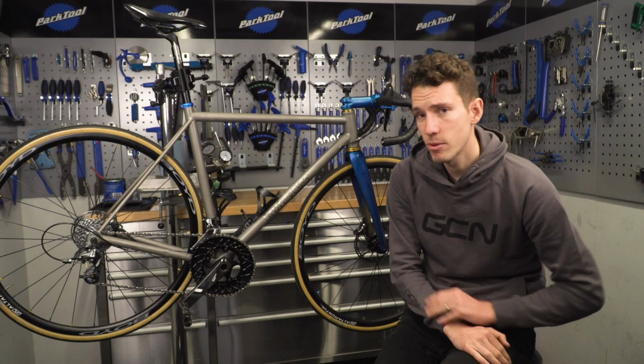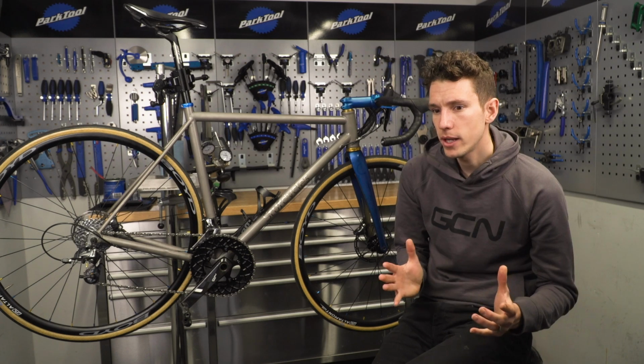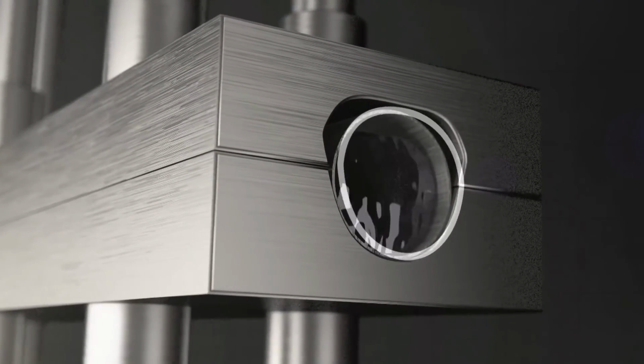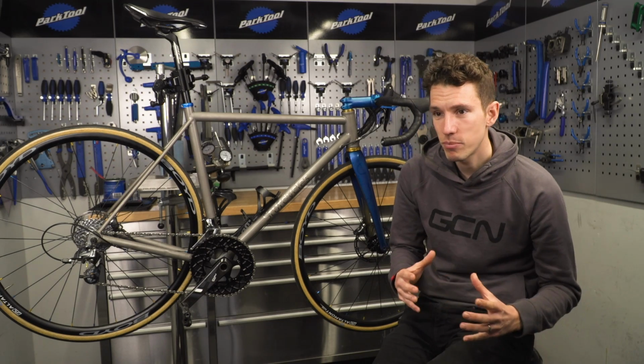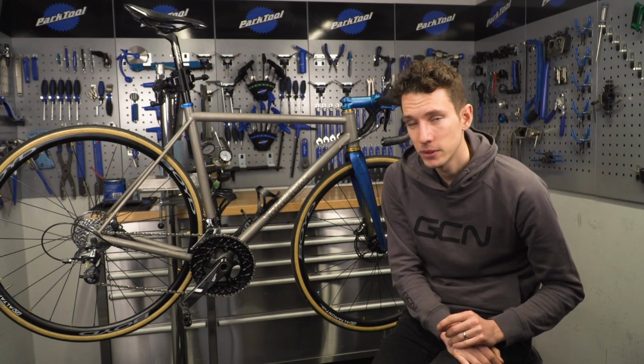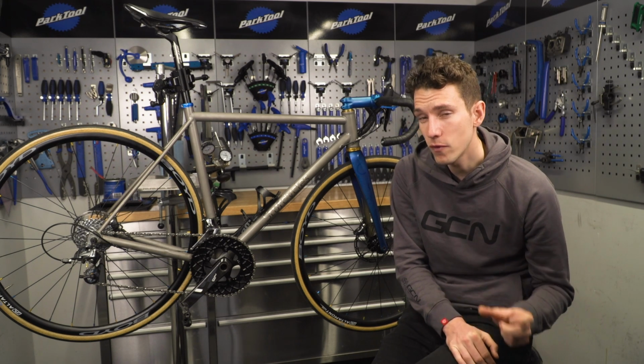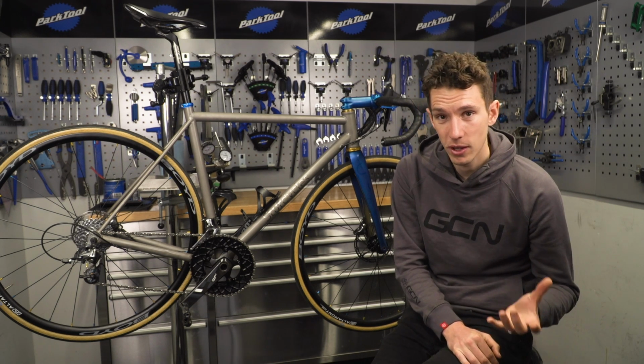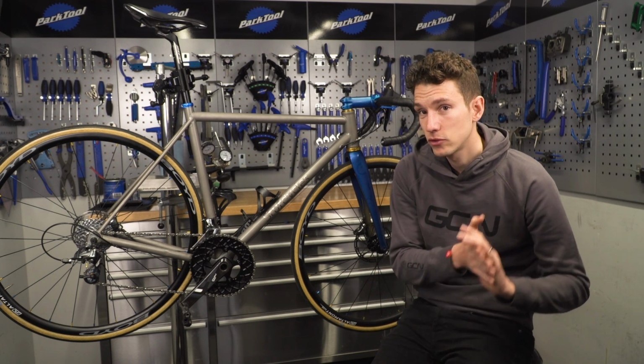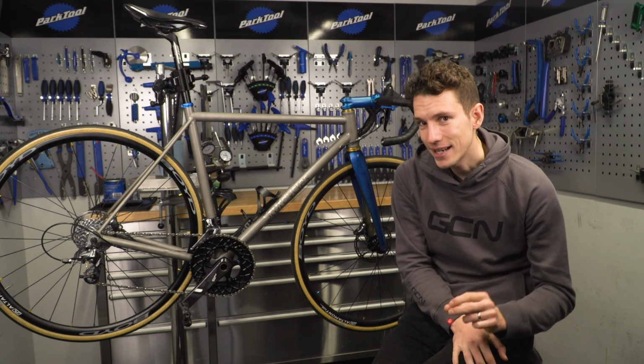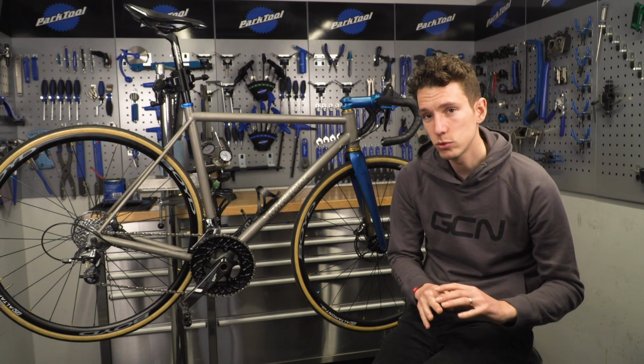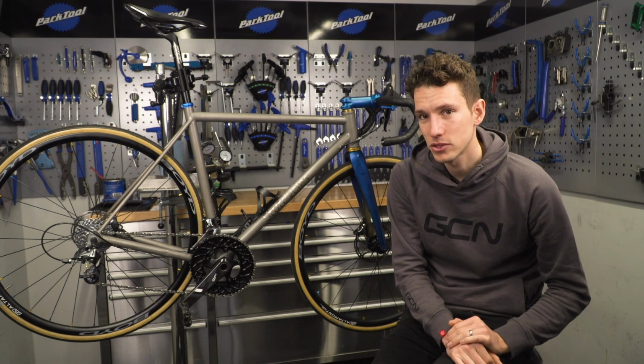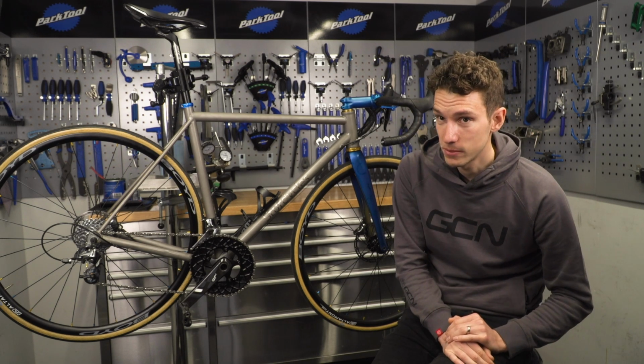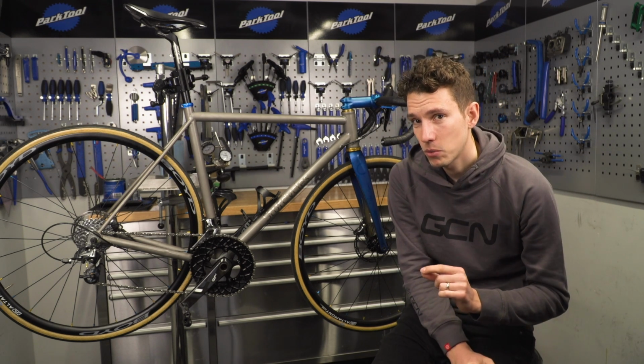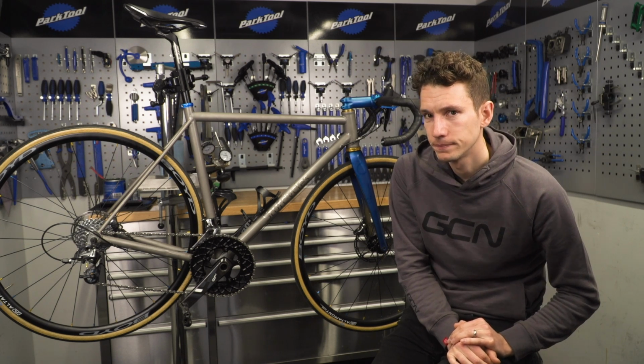The last thing that can make titanium a bit tricky is working. So you see, we mentioned earlier that aluminium can be engineered and manipulated into all sorts of complicated shapes. But with titanium, even bending a simple S-bend chainstay, for example, extreme care has to be taken that you don't overwork the material, which can then lead to it becoming brittle and therefore weak. So in order to avoid that, the titanium needs to be annealed, which is where you heat it up and then you allow it to cool down slowly in between each incremental step of the process. It's quite time consuming, labor intensive, and it's another reason why titanium bikes tend to be quite expensive.